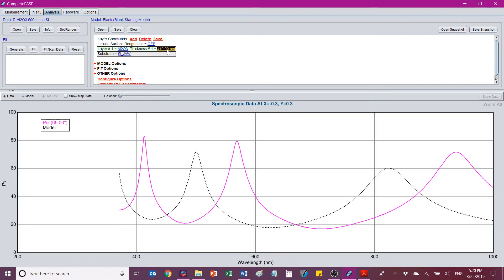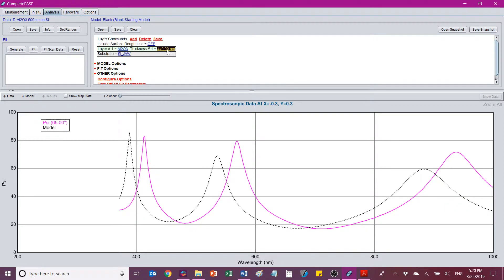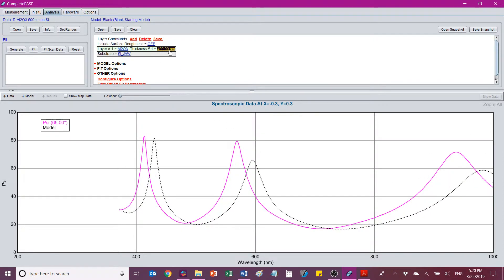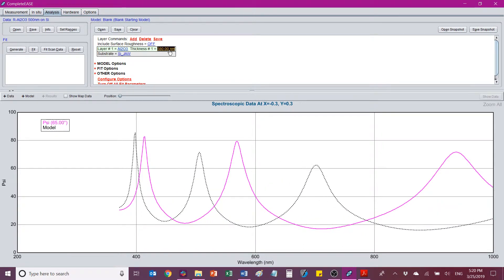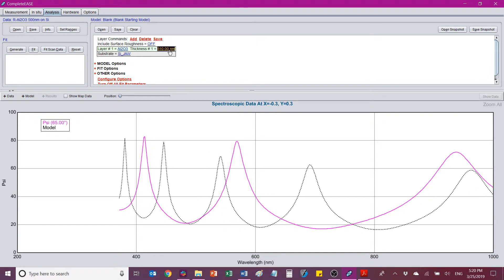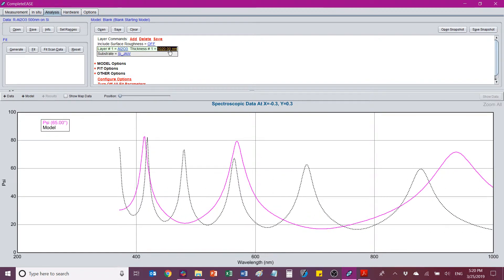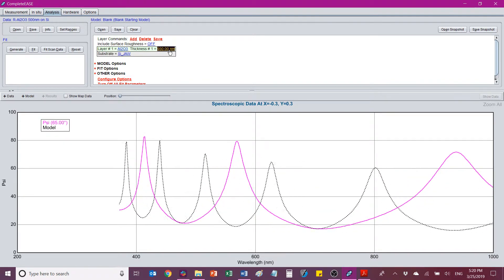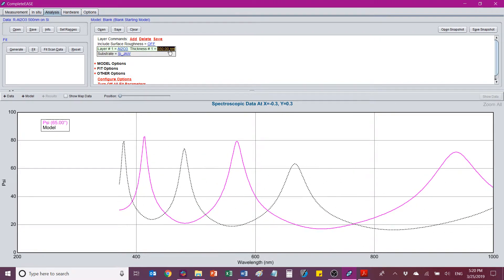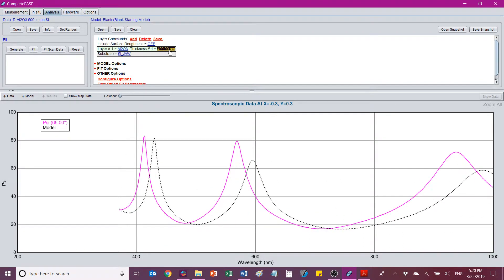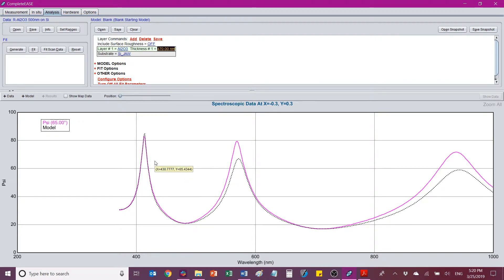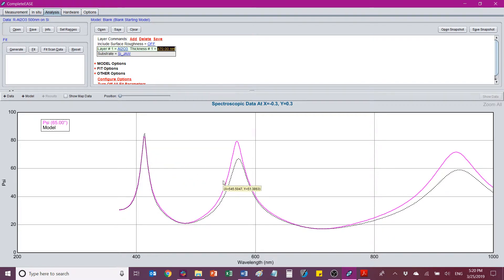So let's try to see if we can change the thickness until this matches. Now at 470, this peak matches, this peak sort of doesn't, and then this peak is kind of similar. If we try to go up a little bit further, we start to see, well, look, as this gets thicker, these interference peaks start to get closer and closer together. So we can see it's definitely thinner. That is to say that the position along the wavelength axis is related to the thickness of these films. But another thing that is related to where these peaks will be located are the optical properties. So the fact that I'm not going to be able to get this to fit is basically telling me that the optical properties, the index of refraction and the absorption that defines this material are not the same as what is captured in this tabulated data file.